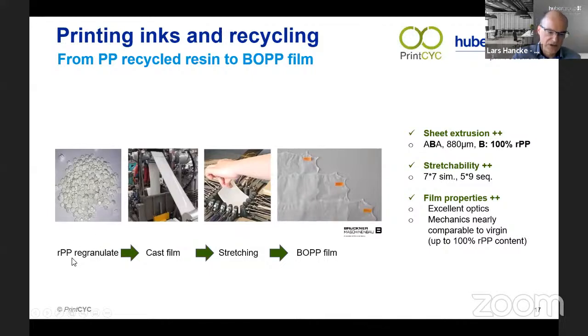The recyclate coming from the printed polypropylene, we converted into cast film in the lab facility at Brückner and did some lab stretching to create biaxially oriented polypropylene. This is quite a critical process with respect to the quality of the starting material, because whenever you have some inhomogeneities, then during the stretching, the film will break.